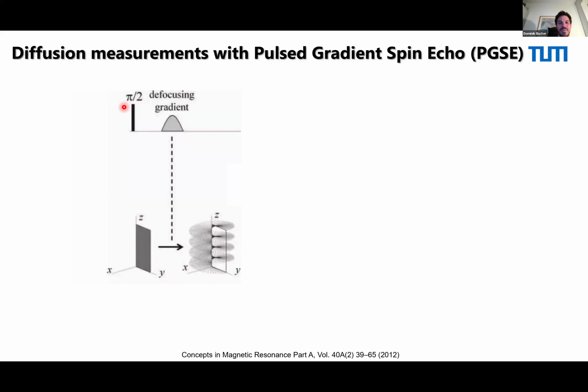So what we typically do is, you have polarized your nuclear spins, and you apply these pi half pulses. Again, very similar with the NV centers. So people who are familiar with NV centers, the same thing, of course, we do in NMR here. So all the spins you see in the space, that's X, Y, Z, will be aligned. So they all get tipped down to the plane. And then you will basically apply a gradient. So that's the most important point. We might apply a gradient.